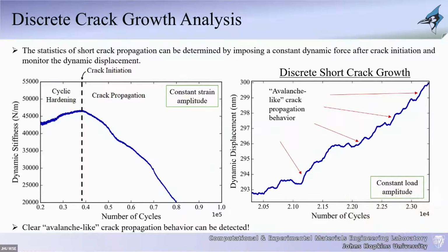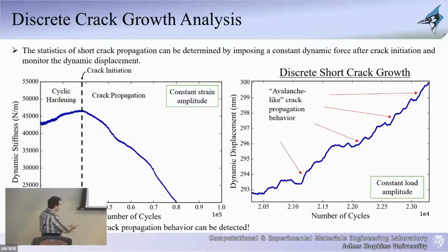And intriguingly, if you look at this type of behavior of the dynamic displacement versus number of cycles after we stop the experiment here before full fracture, you start seeing different types of behavior of that crack. The crack is level, nothing is changing for a while, and then suddenly an increase. Nothing changing for a while, suddenly an increase. Nothing changes for a while, and then suddenly the displacement decreases, which indicates that there's actually crack closure that happens as you continuously cycle the sample. But in addition, it's clear that the way that the crack propagates is through an avalanche-like behavior. The cracks propagate, stop, propagate, stop, propagate, stop continuously. So this was quite intriguing for us to visualize this and be able to measure these types of quantities and statistics associated with it, which I'll skip for now.